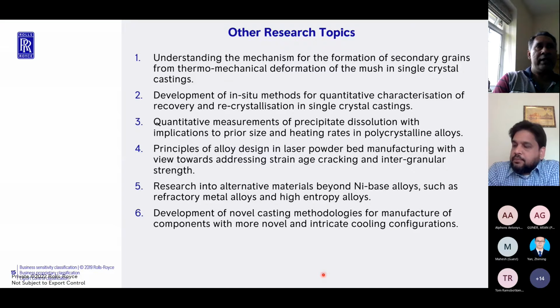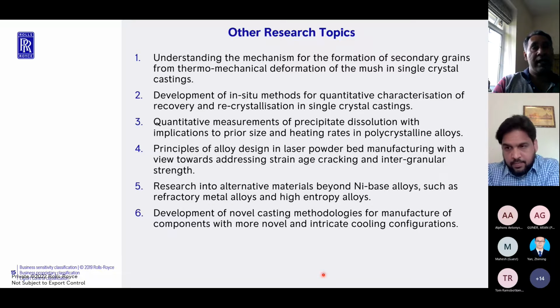Whilst you saw in one of the topics I showed you where we were looking at developing constitutive equations, another method is trying to track recrystallization from the change in the resistance. In other words, an in situ method of tracking recovery and recrystallization during heat treatment. There's some work that I've done recently looking at the evolution and dissolution of precipitates during processing of disc alloys. So this is not single crystal materials per se, but the same concepts can also be used in single crystal materials, effectively looking at resistance-based methods in quantifying phase transformations.